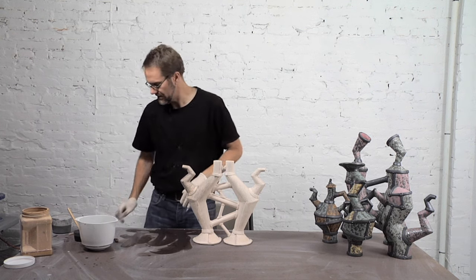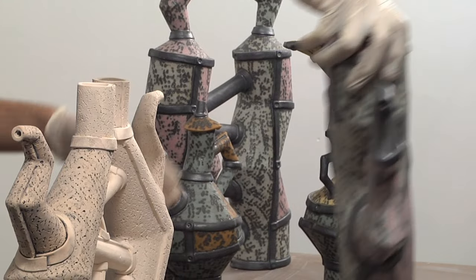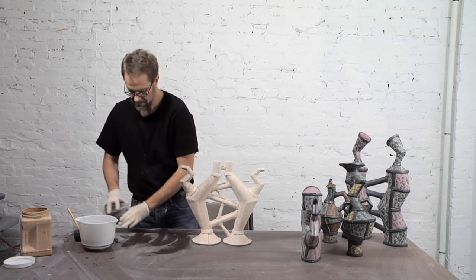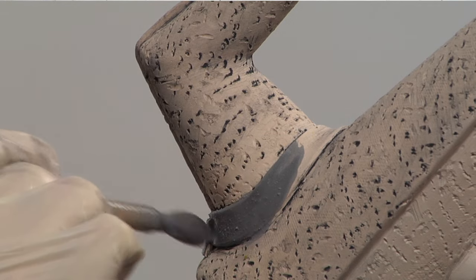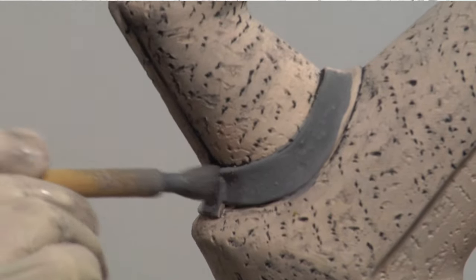You can see how this would be basically on the whole form as we're working on it. The glaze base that I use — I have one glaze recipe and I just use different combinations of oxides, carbonates, and mason stains for them. For the black coloration, where I have the very metallic black in the bands, that is actually my glaze base with 10 percent black copper oxide. The application for that is relatively simple — after the oxide wash has been applied, I go around all the areas of black banding and carefully apply this black copper oxide glaze.